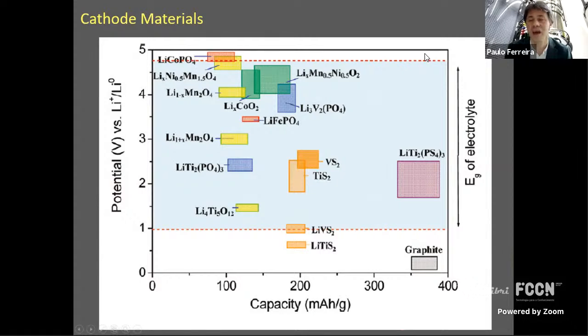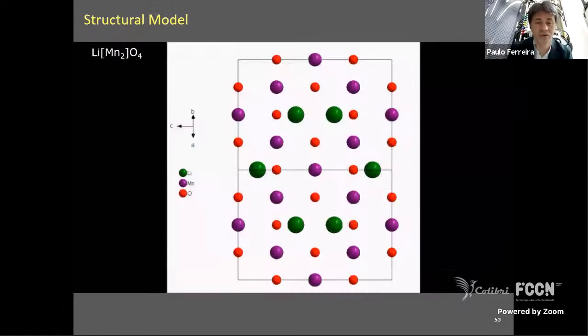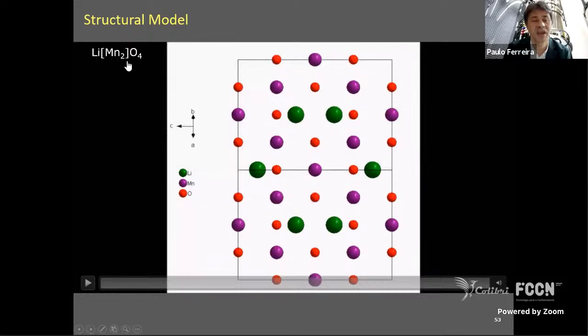So you like to be on the upper right. This is, of course, not easy, and there are a lot of materials here with about 4 to 5 volts, and then about, let's say, 150 milliamp hours per gram. And just to give you an idea in terms of an approach, here's one material which is widely used, the lithium manganese oxide, LiMn2O4.